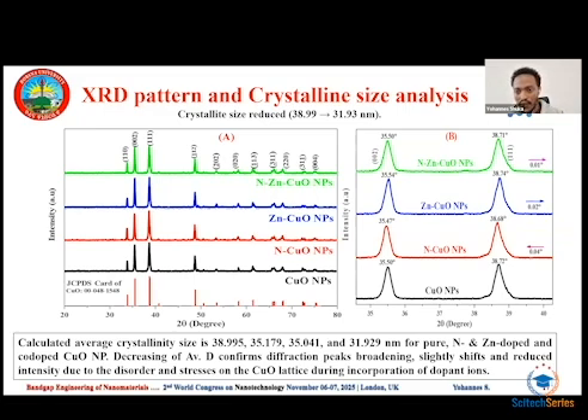The incorporation of these two dopants is clearly observed in the enlarged diffractometry at the right side, and the calculated average crystal size is 38.995, 35.179, 35.041, and 31.929 nanometer for pure, nitrogen doped, zinc doped, and co-doped copper oxide nanoparticles.